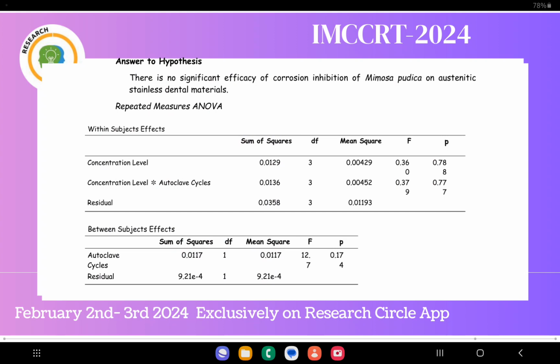Answer to hypothesis. There is no significant efficacy of corrosion inhibition with Mimosa pudica on austenitic stainless steel dental materials. The analysis of variance, ANOVA, with repeated measures was conducted to assess the corrosion inhibition efficacy of Mimosa pudica on austenitic stainless steel dental materials. The within subjects' effects were examined for both concentration level and the interaction between concentration level and autoclave cycles. For concentration level, the F statistic was 0.360 with a p-value of 0.788, suggesting no significant impact on corrosion inhibition.